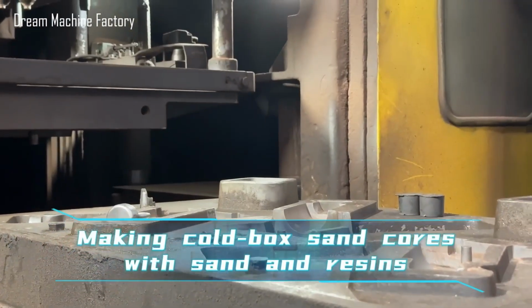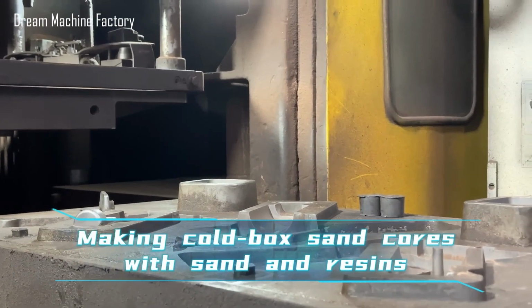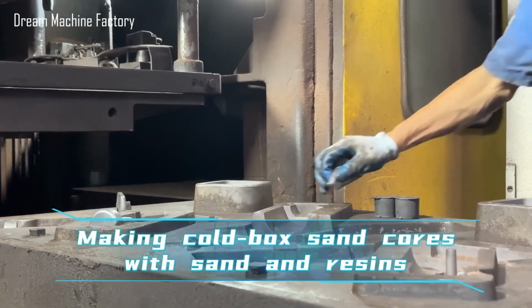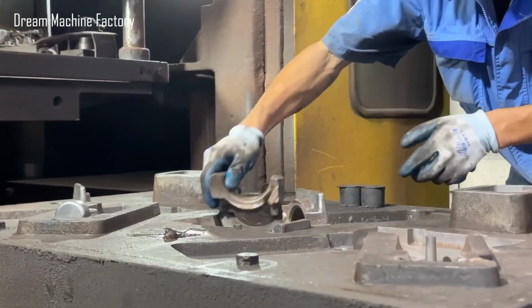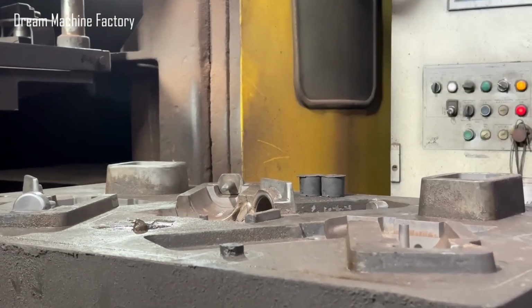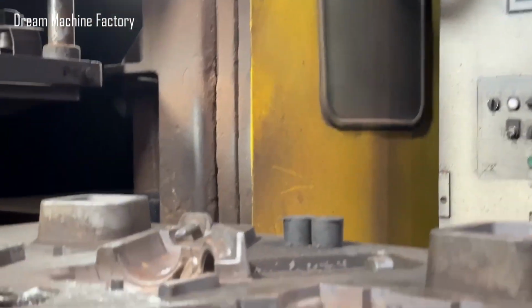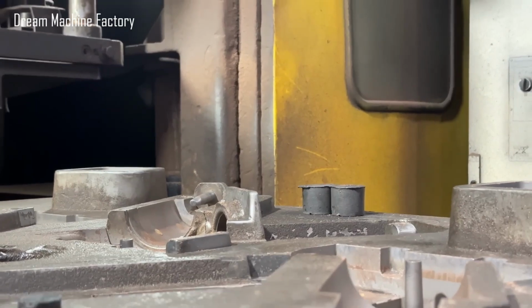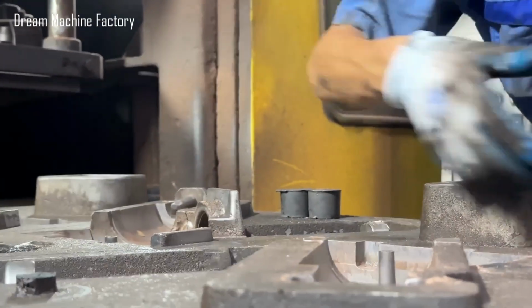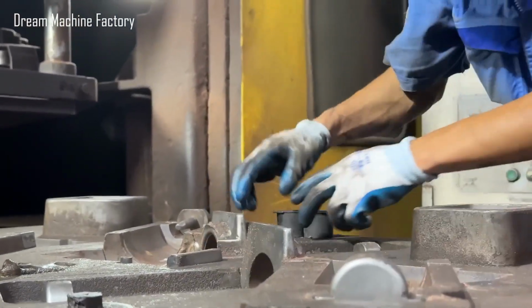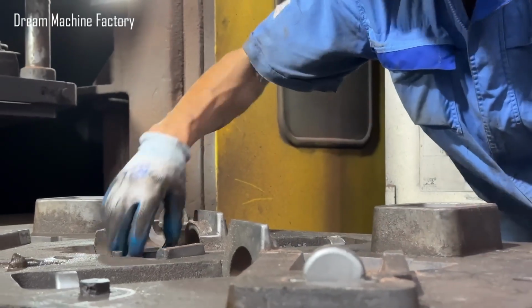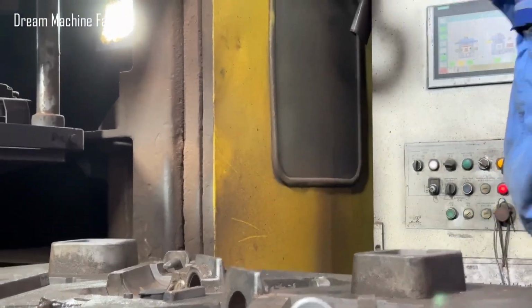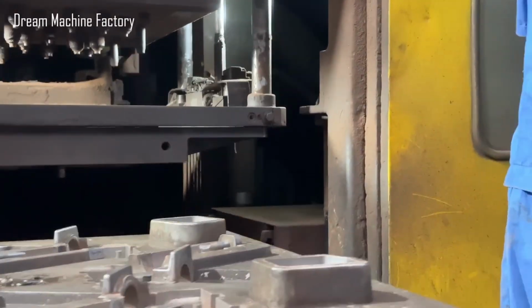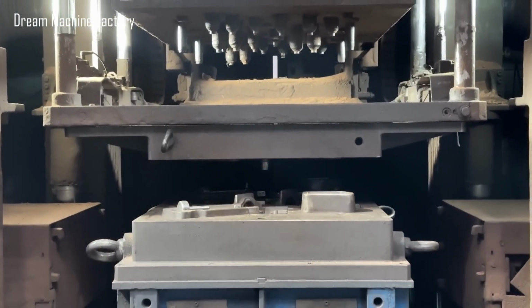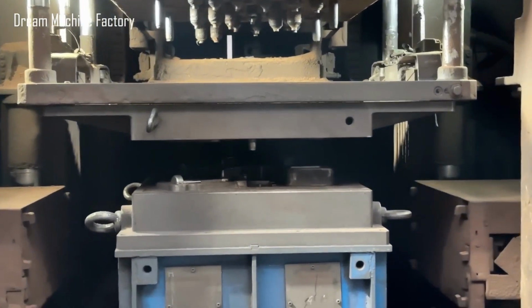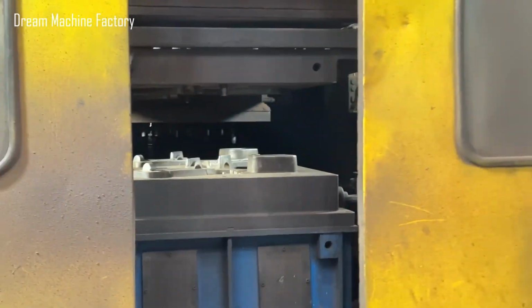In the cold box process, dry silica sand is mixed with a two-part resin binder system, typically polyurethane-based. This mixture is blown into a metal core box, where it conforms to the desired shape. A reactive gas, usually amine vapor, is then injected into the cavity, triggering a chemical reaction that rapidly hardens the core at room temperature. This method produces strong, precise cores with excellent dimensional stability, and is ideal for high-volume production of intricate engine block features.